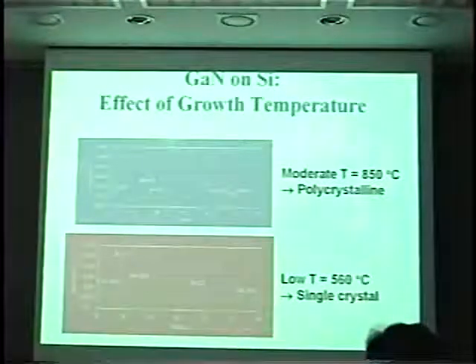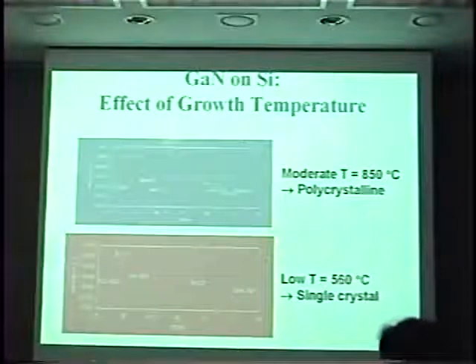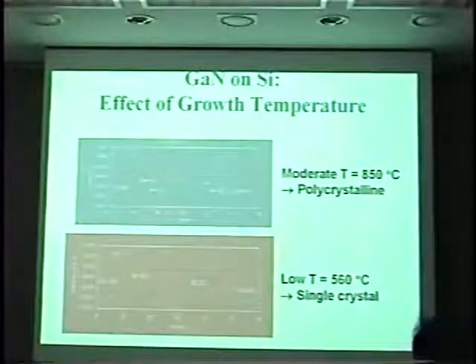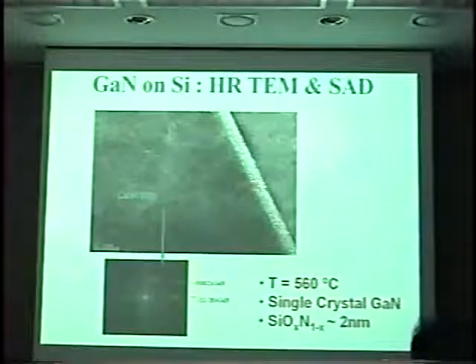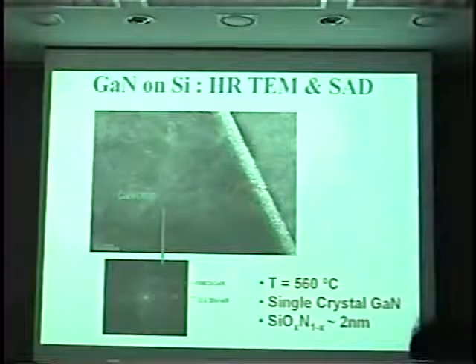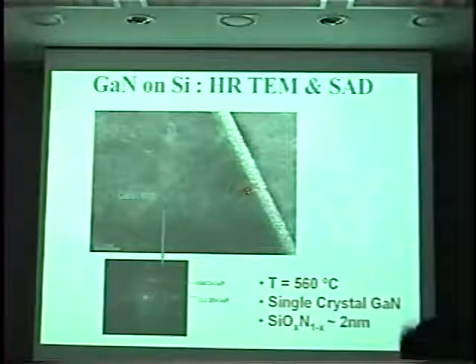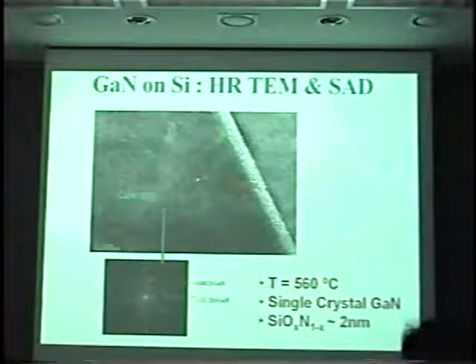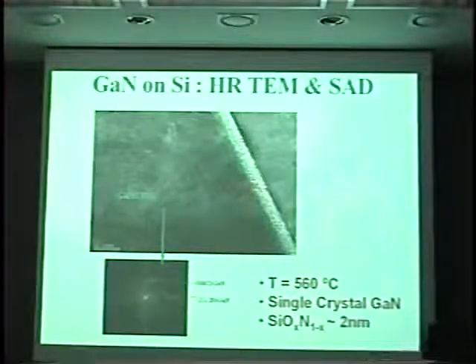Well, here's what we did. Again, comparing what we got at 850 to what we got at 560 degrees C, voila, we have single crystal gallium nitride of relatively high quality. So this technique apparently avoids the formation of the silicon nitride interface. This is further verified by a high-resolution TEM micrograph that shows the lattice image of silicon 111. It shows a 2 nanometer, 4 or 5 layer silicon oxynitride interface, and then, of course with a small area, high quality gallium nitride C-oriented material.